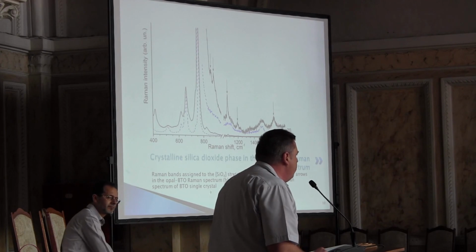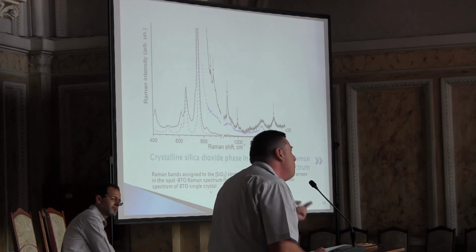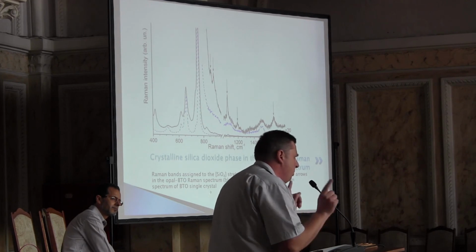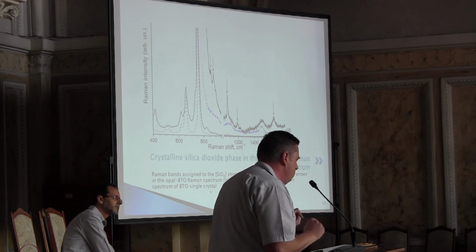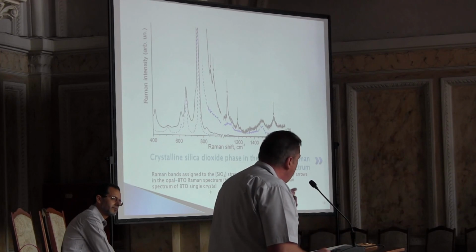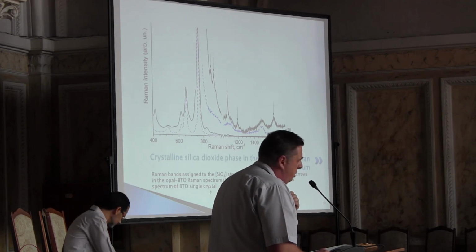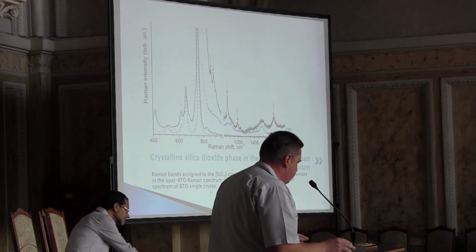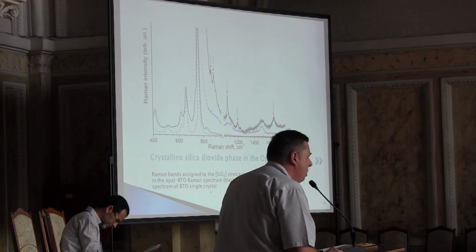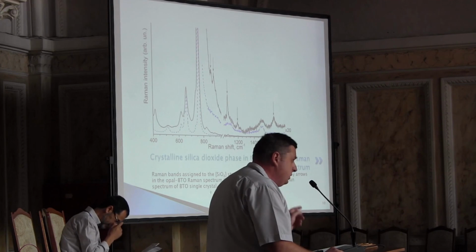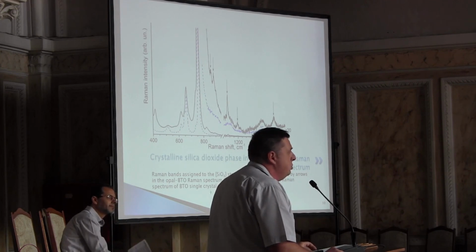We have activation energy. We propose electron conductivity, but we are not sure by now. We have an activation energy of about 1 electron volt, and the dielectric constant at 1 kilohertz of this composite was equal to 2.